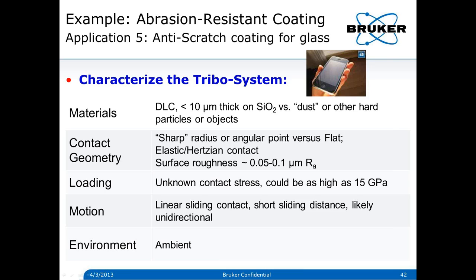Probably two more examples in the allotted time. An abrasion-resistant coating is very popular these days — most cell phones and tablets have a touch screen that we rub with fingers. You can also have debris: small dust or sand particles that can be quite abrasive and scratch the glass. We worry about those particles. Typically we'd put a hard coating on it; diamond-like carbon (DLC) is commonly used, less than 10 microns thick, probably less than 5 microns.